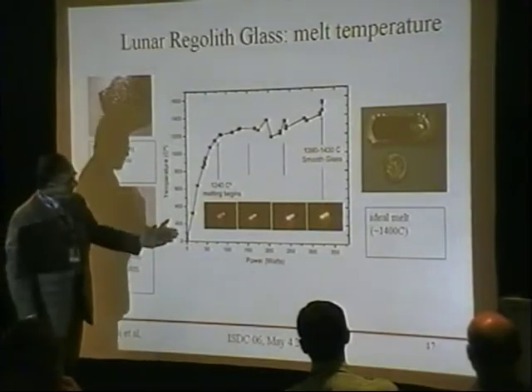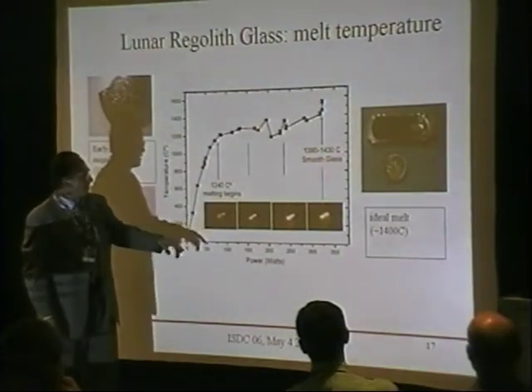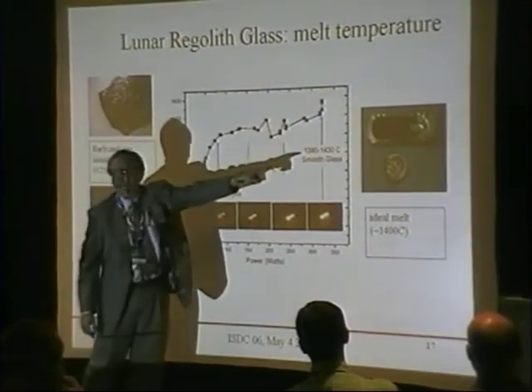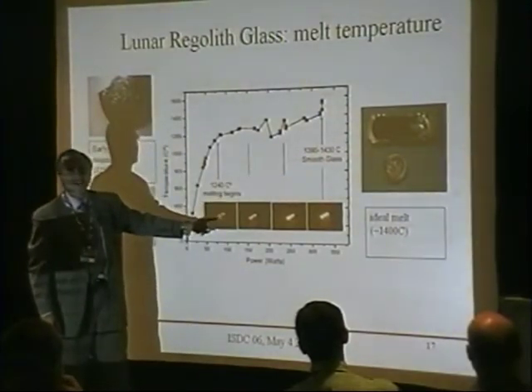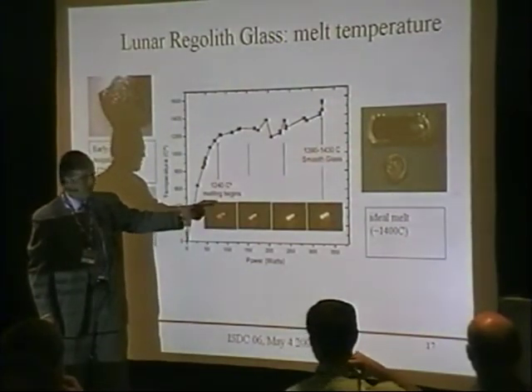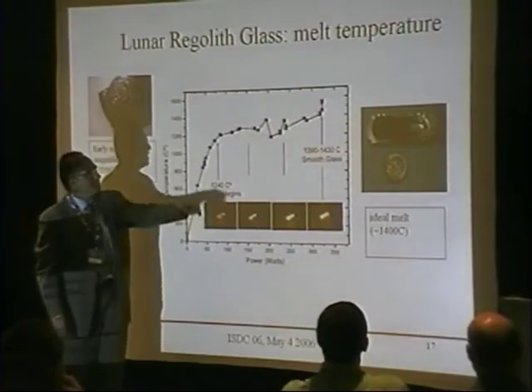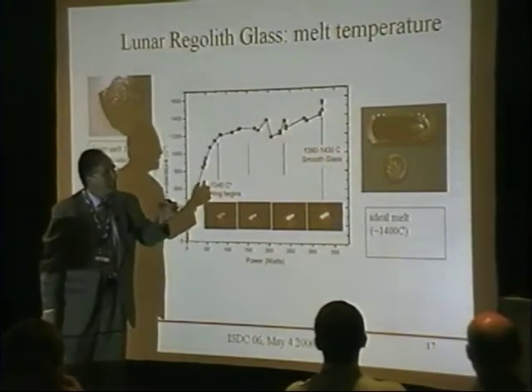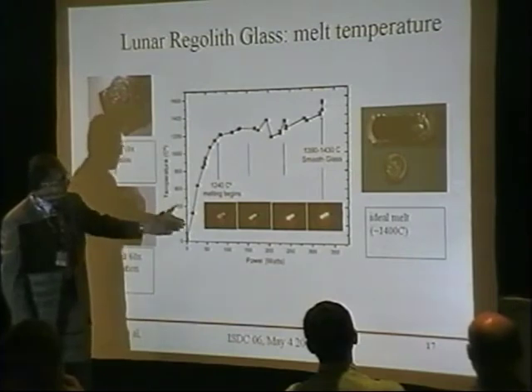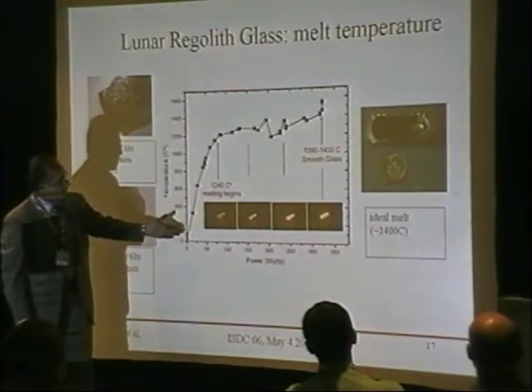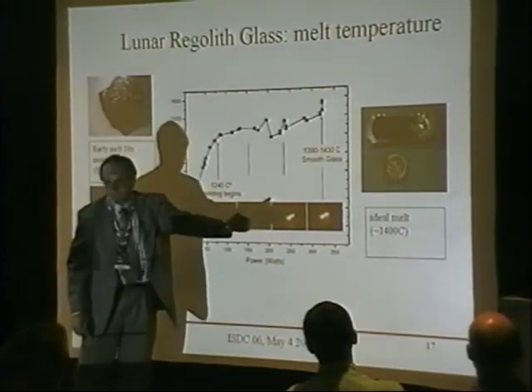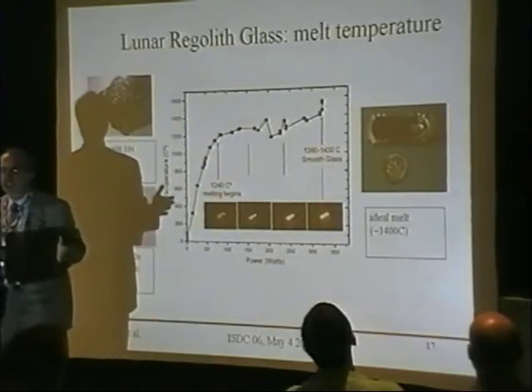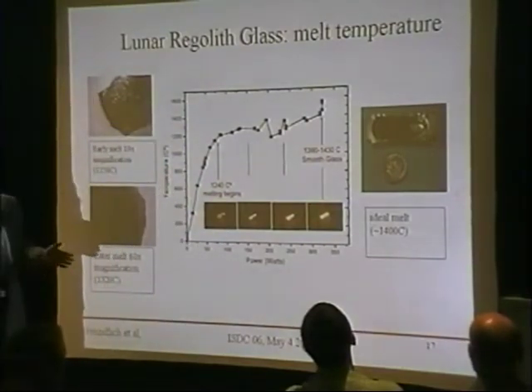As you can notice, as a function of the power that's supplied, this one is not the same as there. Now we're working at larger sizes, about 2 by 4 centimeters, and this one used to be a little bit tiny. Essentially, we need roughly 50 watts of power per square centimeter to melt this regolith appropriately.